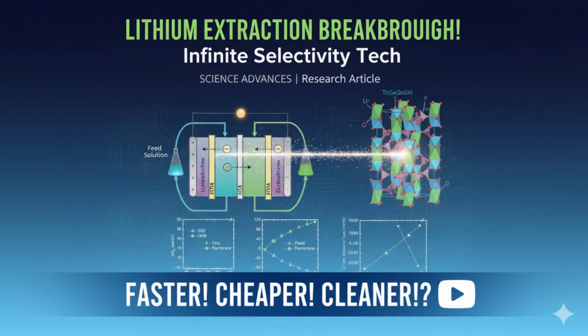Ah, yes. That's a really important practical point. So the selectivity is essentially perfect, zero permeation of competitors. But the rate at which lithium ions cross the membrane, the lithium flux, can be affected by what else is in the solution. How does that work if they aren't going through? They basically crowd the entrance. Imagine our exclusive nightclub again. Even if the wrong people can't get past the bouncer, if there's a huge mob of them blocking the doorway, the eligible guests, the lithium ions, have a harder time getting to the entrance and going inside.